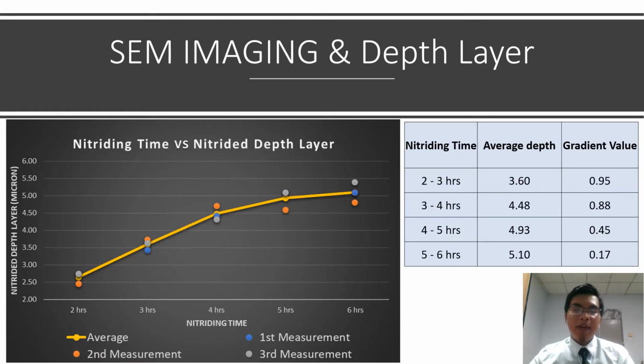Here is the line graph representing the tabulated data given just now. The orange line here represents the average value of the nitride depth layer. As you can see here, from 2 hours to 4 hours of nitriding time, the depth layer formation occurs at the same rate. However, after 4 hours of nitriding, the nitriding becomes a little bit slower, and after 5 hours, it becomes even slower than the previous one.